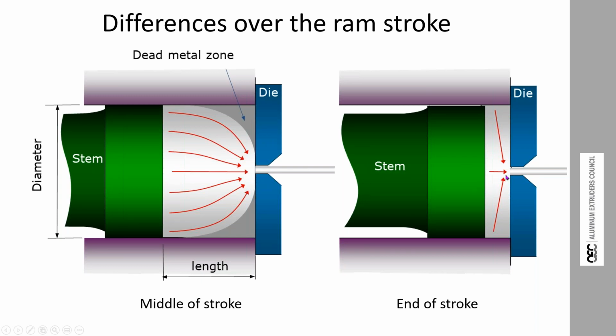And when we get really close to the end of the stroke and we're just short of the last little bit before the butt comes, you can see we're totally constrained. It's a totally different environment. And that's why you'll often see a little leg at the end of the extrusion do this sort of wave. Hopefully in the scrap section, you're going to lose to stretching, but I always call that the section waving goodbye.